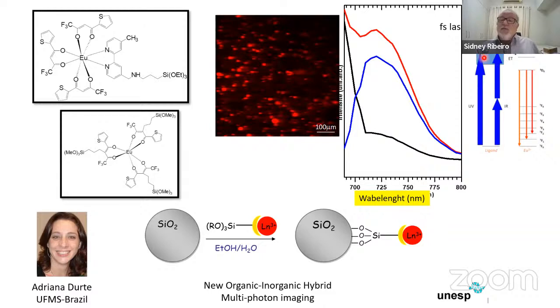So you can get to these levels either with a UV lamp directly or with an infrared laser in a two-photon process, as I show schematically here. By doing that, you can use femtosecond lasers emitting in the infrared in order to populate these ultraviolet levels and observe the visible emission of europium. So this is the excitation in blue here. You have the excitation spectrum obtained in the infrared region of the spectrum.